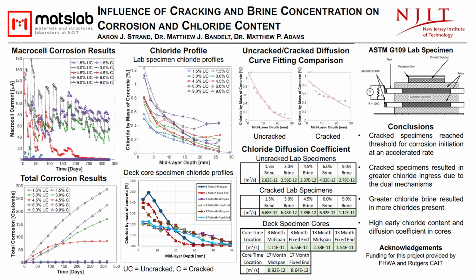From the chloride profile data, the concentration of brine does seem to impact the amount of chlorides that were found within the samples at a given layer. The higher the brine concentration, the higher the chloride content that was found. Near the surface, the chloride content was similar between the cracked and uncracked conditions of each of the brine levels. The biggest difference was observed between the 6% brine cracked and uncracked specimens.